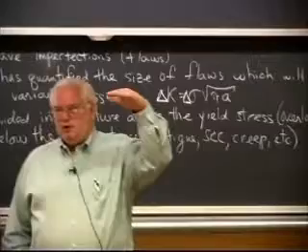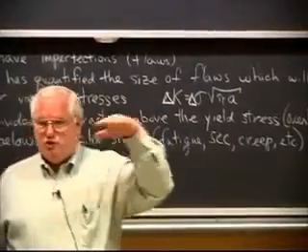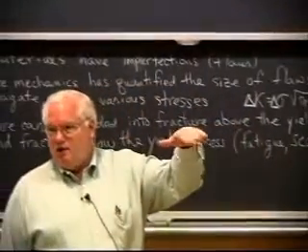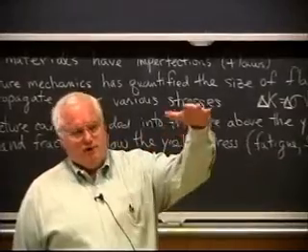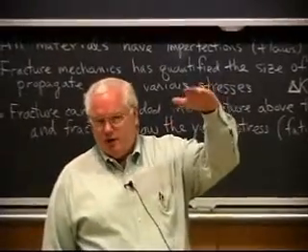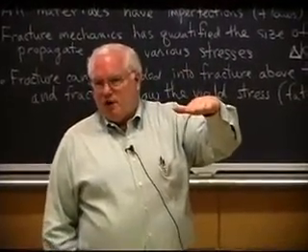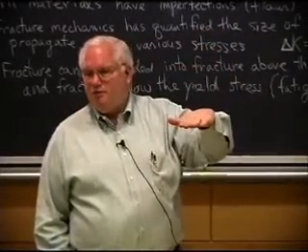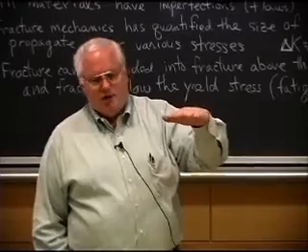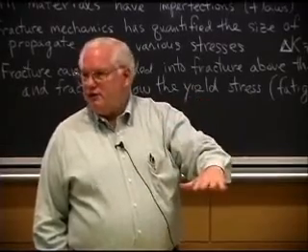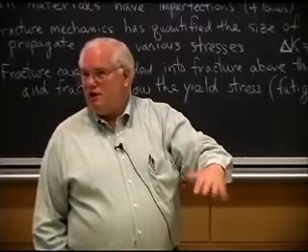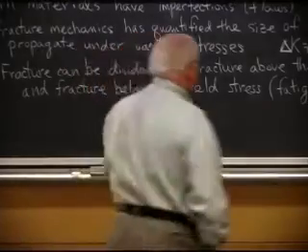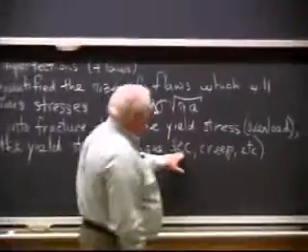Typical fatigue stress for the 7075 T6 aluminum should have been like 35 KSI for a practical fatigue limit. It doesn't have a true fatigue limit, but you ought to be able to operate it there. Since it's got 73 KSI strength, you ought to be able to operate it at 50% of that, like 35 KSI. But in fact, it failed at 8 KSI. Why? Because you had corrosion going on too. So stress corrosion cracking can be very insidious.